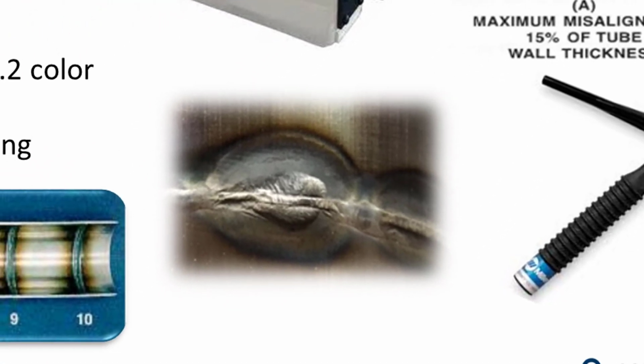Just an example of a poorly done weld. There's a lot going on there. That one happened to have the situation of it was too much heat in the tack weld. We talked about that yesterday some. As we're doing tack welds, we want that weld only to not penetrate all the way through. We want it just to be on the outside surface. If we penetrate all the way through, we have the situation of creating a poor platform for the weld to continue to penetrate as we're doing the full weld.